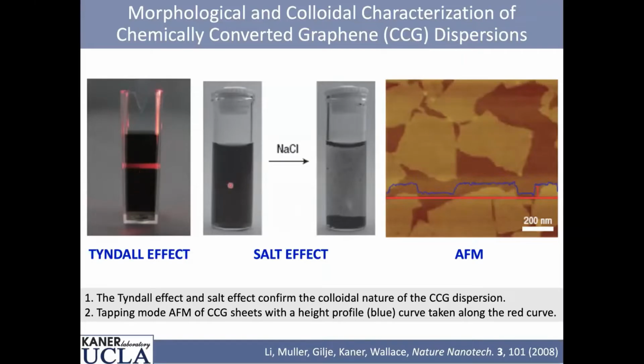How do we know that? Well, we can get rid of the charge using any salt. So if we throw in sodium chloride, it flocculates out because we just knock out the surface charge. And we know it's graphene because it has all the attributes of graphene, being carbon and being very thin.